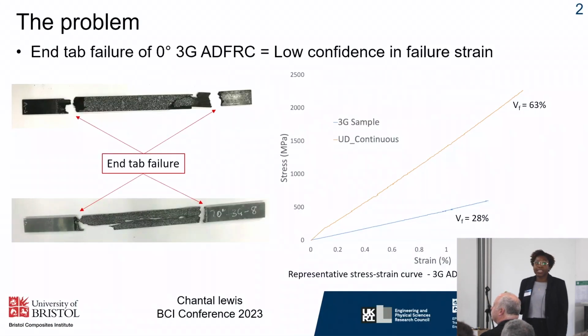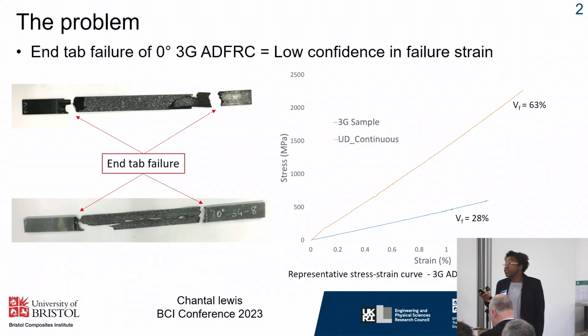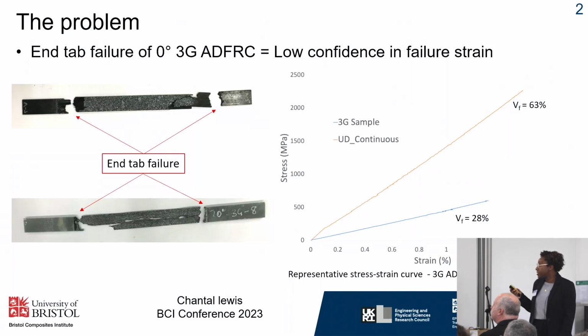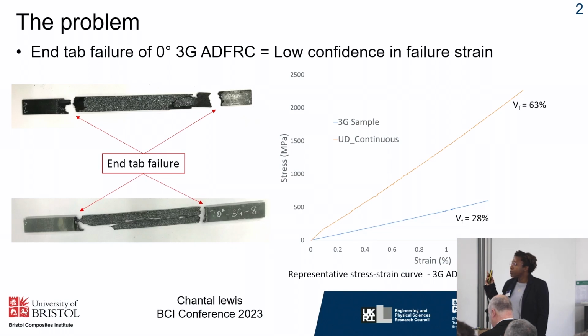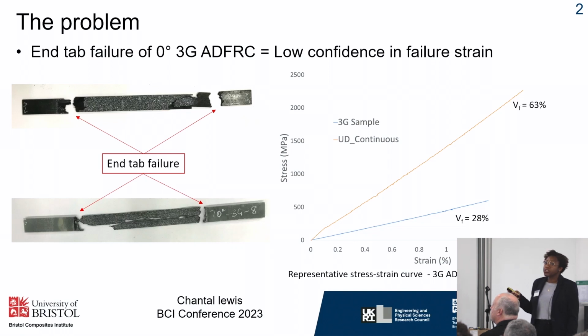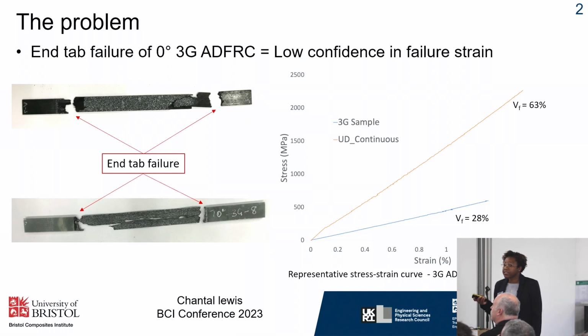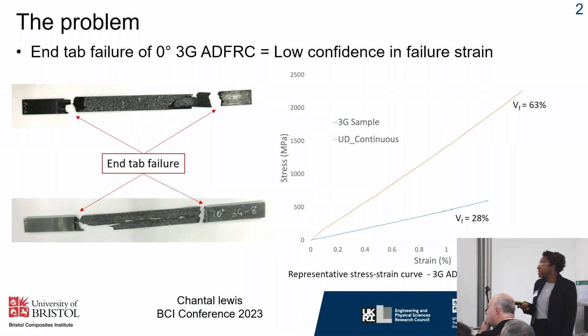So the problem is during tensile testing, the ADFRC specimens are prone to premature specimen failure, and this is because of the high stress concentration that occurs around the gripping region because of the localized stress transfers from the gripping area to the rest of the specimen. As a result, the failure strain that is achieved is not really a reliable representation. You can see two different specimen configurations were tested, and both of them failed around the end tabs. The results were also compared with unidirectional continuous composites of similar constituent materials and shown to be much lower.